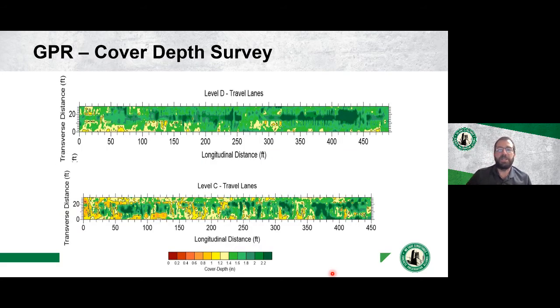Here's the cover depth survey conducted on the parking garage in Washington, D.C. And you can see that on level D and level C, we have the travel lanes for the garage that we scan. And we can see that in the travel lanes of C, we have a lot more areas of lower cover depth, less than 1.5 inches, whereas with the level D, most of the area is above 1.5 to 2 inches deep.